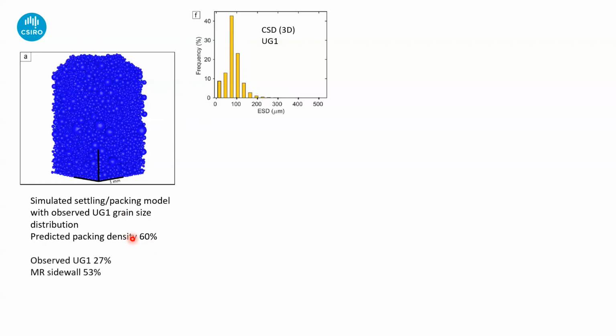Now, if we compare that with what we actually see, that UG1 sample that I showed you is actually 27% crystals. That Merensky Reef sidewall sample is 53% crystals. So they're both considerably less than the theoretical packing density for just basically dropping loose crystals in a bucket.